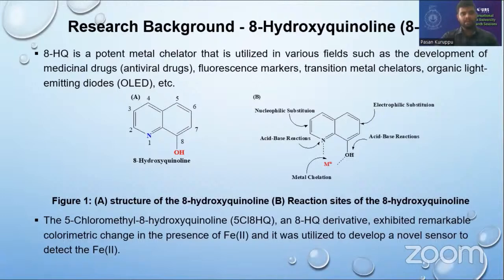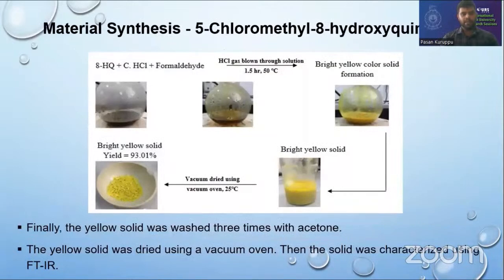So let's move on to the material synthesis, the 5-chloromethyl 8-hydroxyquinoline. 0.05 mole of 8-hydroxyquinoline was mixed with 8 milliliters of concentrated hydrochloric acid and 8 milliliters of 37% formaldehyde. And the reaction mixture temperature was increased to 50 Celsius. And hydrochloric acid gas was bubbled through the solution mixture for 1.5 hours. Then there was a sudden color change from brown to bright yellow. Then it was stirred for 6 hours. Afterward, it was allowed to settle overnight.